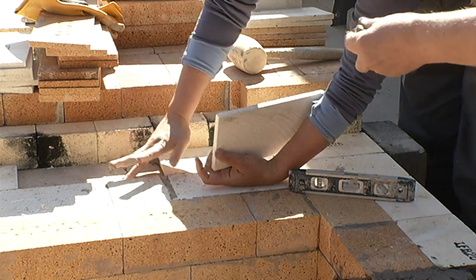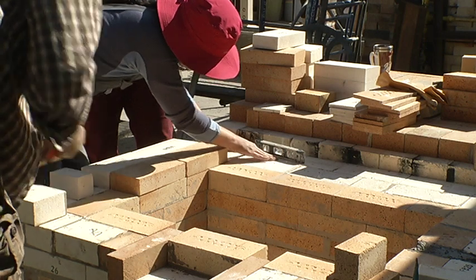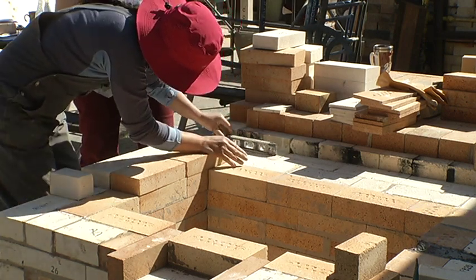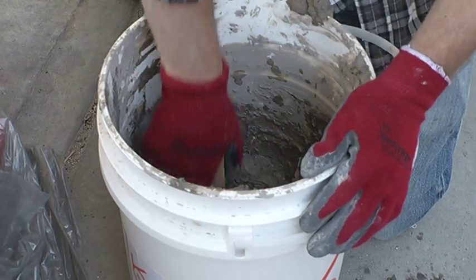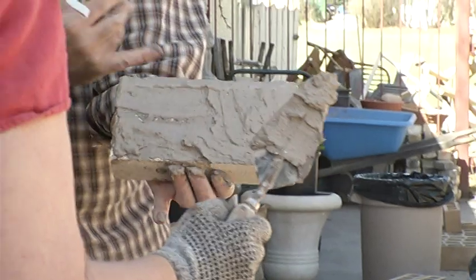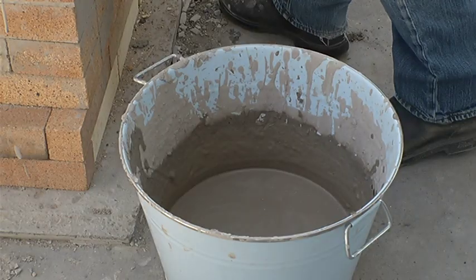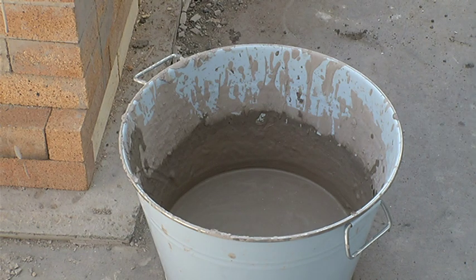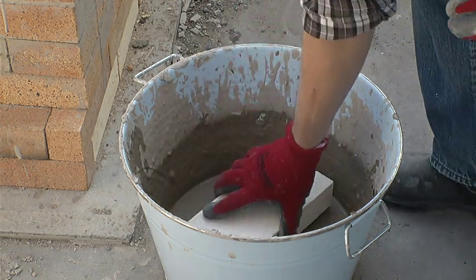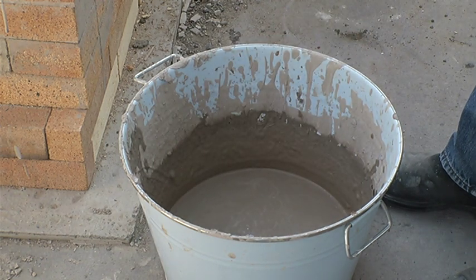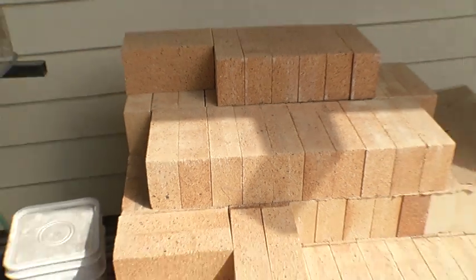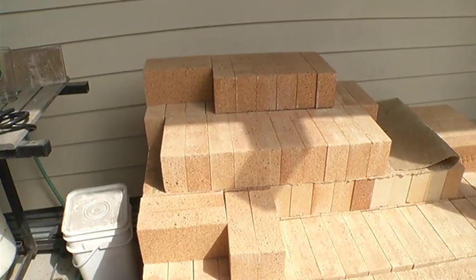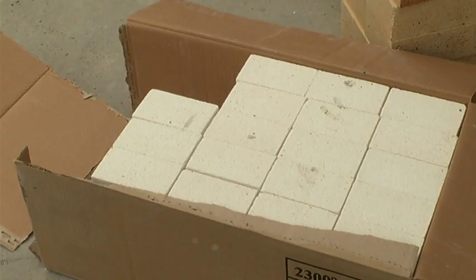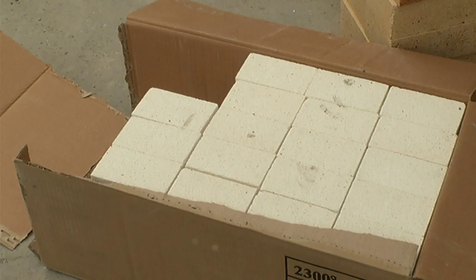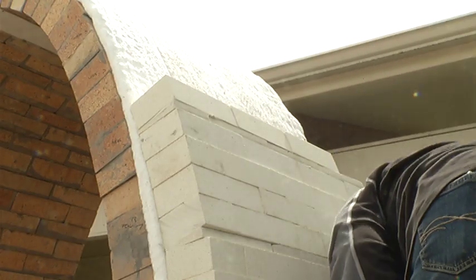This mortarless construction means every brick has to be leveled both to itself and to all the surrounding bricks on its level. We used clay sand mix to level inconsistencies and to provide large fill areas between the bricks. And we used a thin slip for gas seals. This slip was of a fire clay mix so that it could withstand the temperatures of the kiln and not be burned out. For the kiln construction, we used 2 types of brick, a hard, durable brick to withstand the atmosphere of the fire itself, and a soft brick for insulation. The kiln has a hard interior shell with an insulating exterior shell of soft brick to keep the heat in.